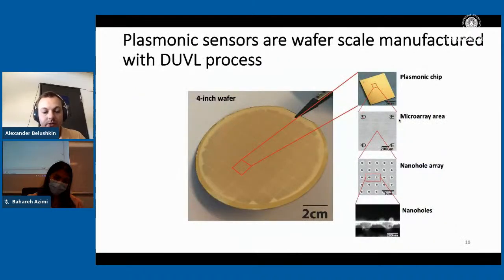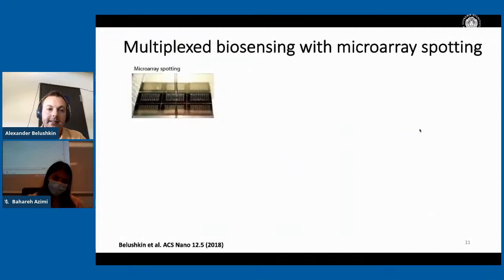It's also important that the gold nanohole array chips are fabricated with scalable wafer scale manufacturing that uses deep UV lithography and ion beam etching, which yields around 50 chips from a single 4-inch wafer. That's really critical for translating the technology to in-field applications. The next step for us was to develop a multiplexed array, so basically we want to detect several things at a time.